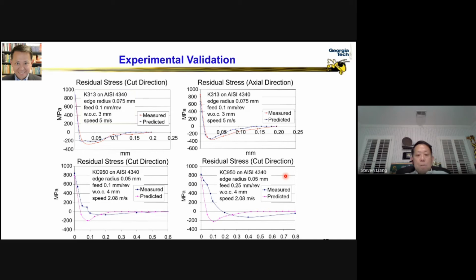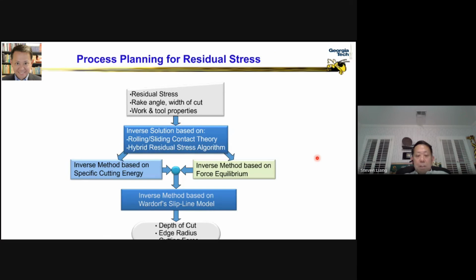And what is also quite important is the reverse engineering process, right? If the technology user is interested in knowing what combination of process parameters, what choice of depth of cut and tool geometry will guarantee the residual stress, then the analysis is totally reversed. In our case, because our analytical model is completely analytical, physics-based, and in closed form, we are able to reverse our analysis to use residual stress specifications, for example, compressive residual stress at the surface to how much depth, as the input. And then the calculation will come out to advise what would be the best choice of depth of cut, cutting tool geometry, and so on and so forth.